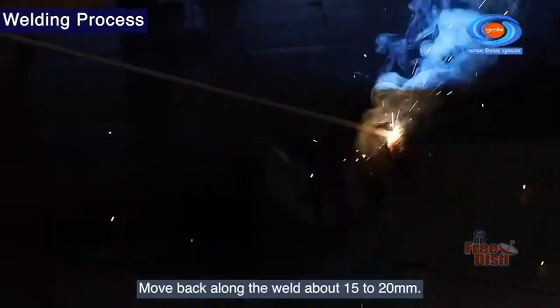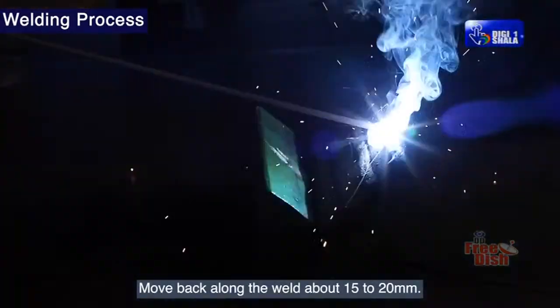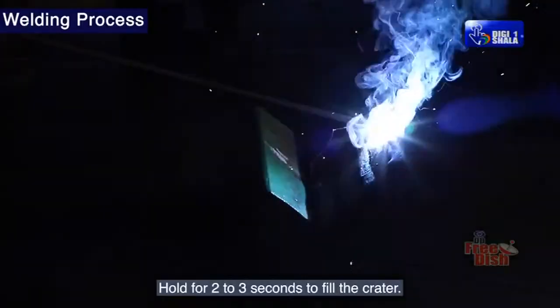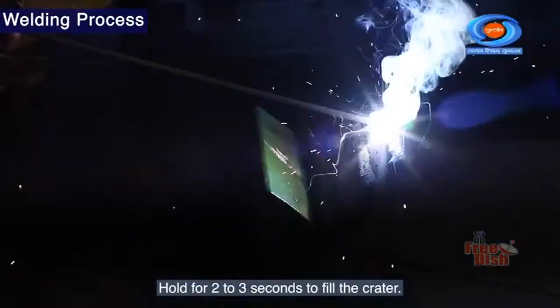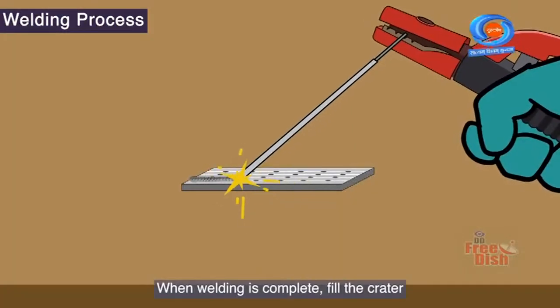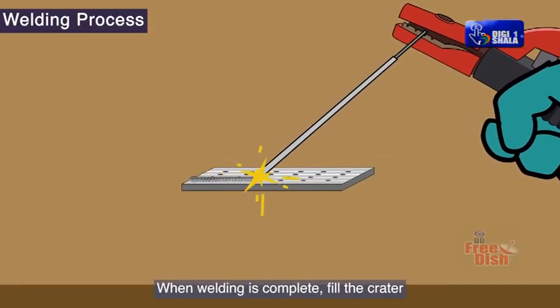Move back along the weld about 15 to 20 mm. Hold for 2 to 3 seconds to fill the crater. When welding is complete, fill the crater.